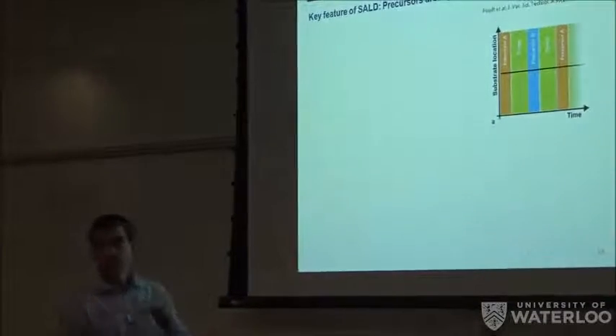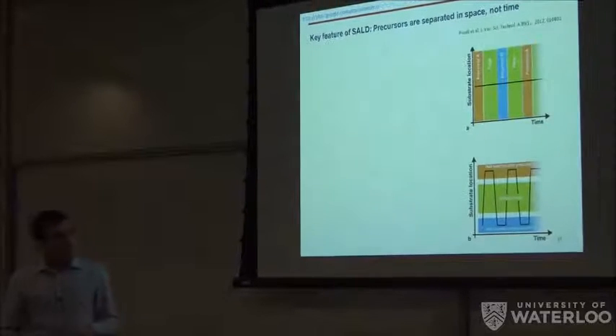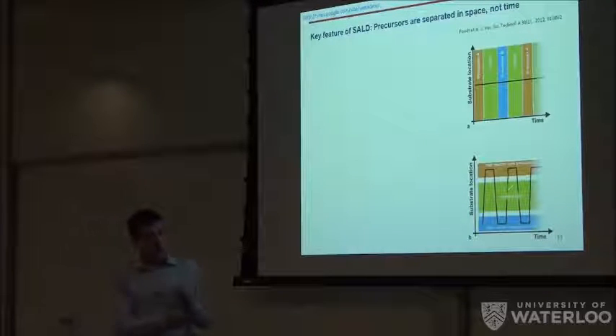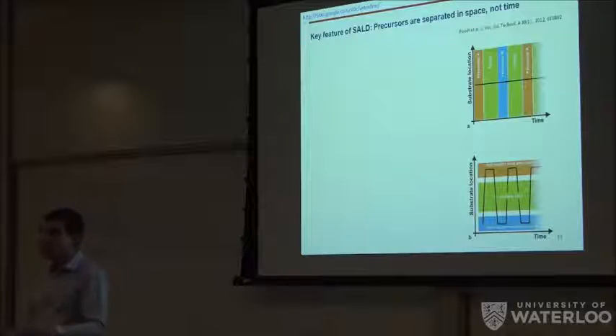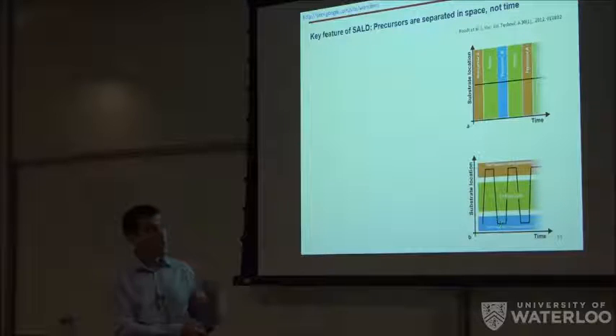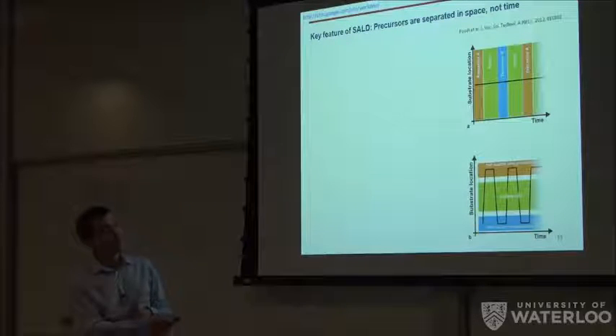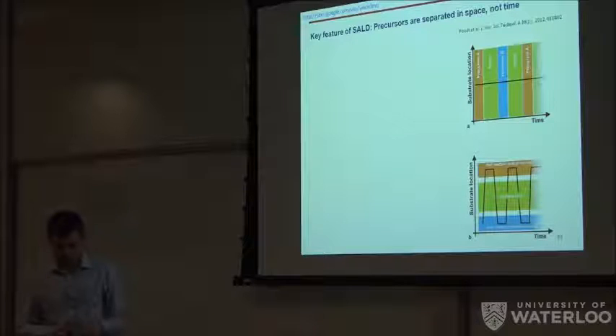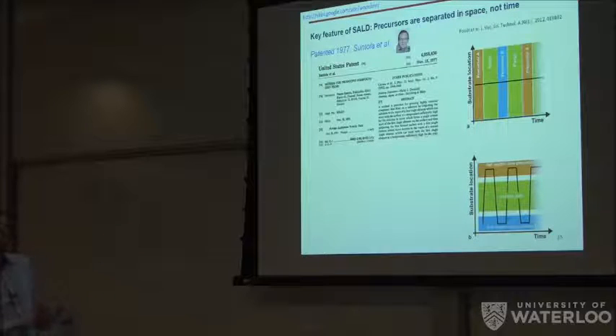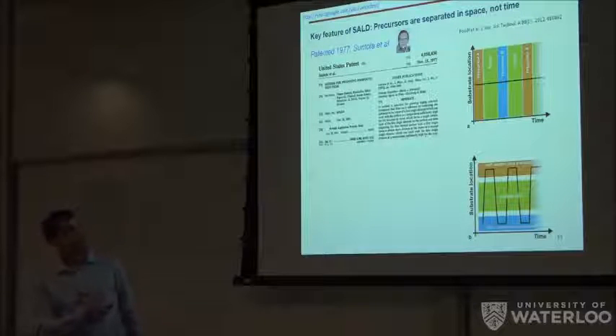So what would be the solutions for that, so that we can use it even in industry? Well, the solution is to go from this. This is the scheme of conventional ALD that I have been explaining, in which you inject the precursor, you purge, you inject the second, and the sample stays still in the reactor. What you can do is inject the precursors continuously in separate locations, kept apart by an inert gas flow, and it is the sample that goes from one to the other. As it does so, it replicates the conventional ALD cycles because it goes through this inert gas zone, and that cleans the surface. Funny enough, both approaches were already published in 1977 by Suntola in Finland.